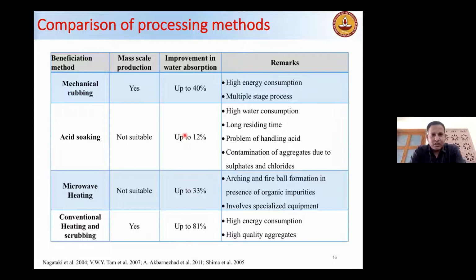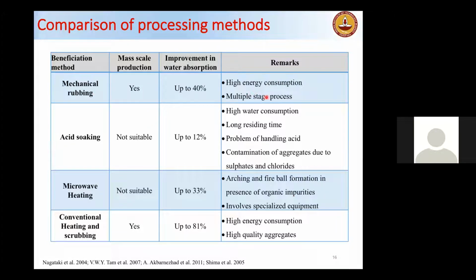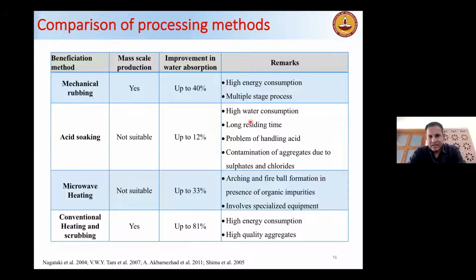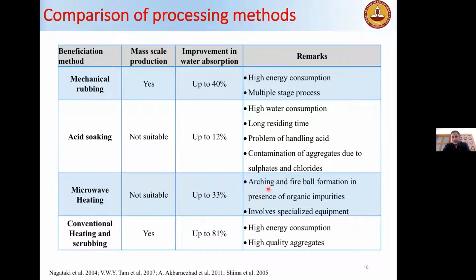So let me give you a comparison of the different processing methods based on what is the state of the art available today. So there could be positive and negative remarks for each method. Like mechanical rubbing, we have high energy consumption, multiple stage process. Acid soaking has high water consumption and problem of handling, and there could be contamination of sulfate and chloride, which could be a durability problem. Microwave heating has this arcing and fireball formation, and it involves specialized equipment, of course. And conventional heating and scrubbing, as we can see, it has mass scale production ability, and the improvement in water absorption is high, up to 80%, but there is a high energy consumption, but you get the high quality aggregates.